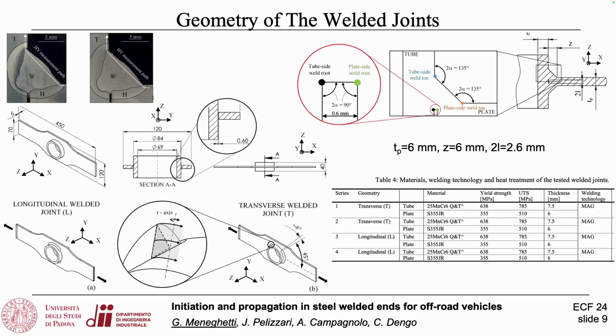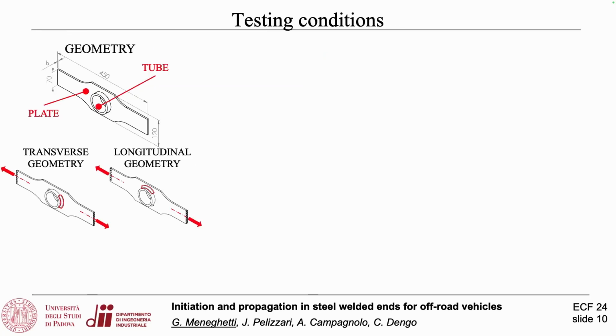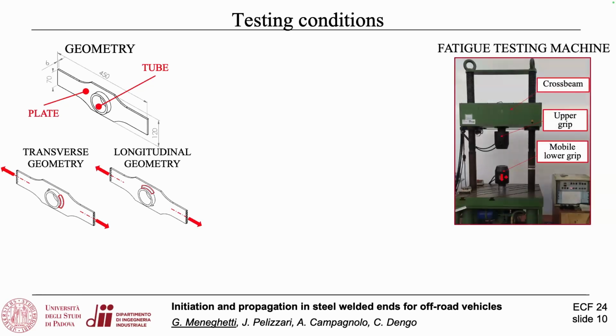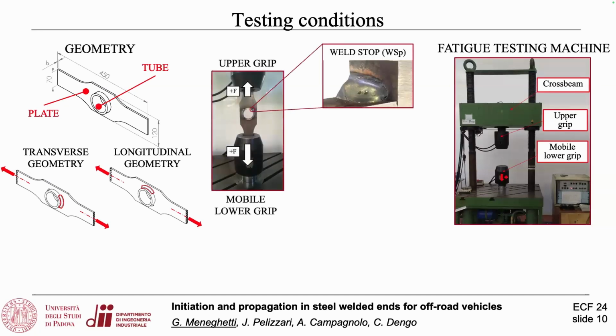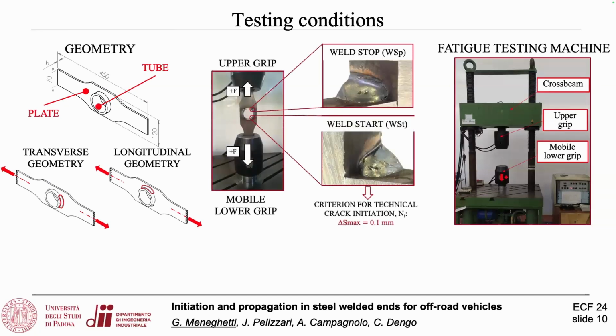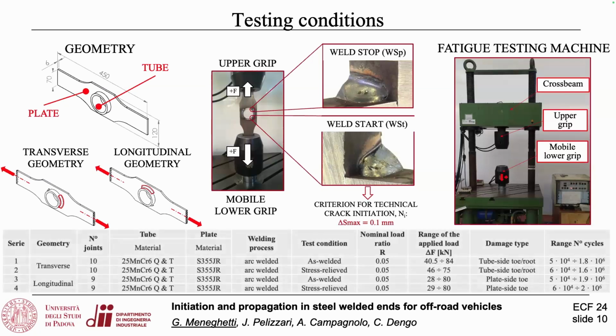We designed 2 versions of the specimens, one with intermittent welds which are almost parallel to the loading direction, and the other one where the intermittent welds are transverse to the loading direction. And this determined the name given to the geometries, longitudinal and transverse joints. So this is the joint geometry. The testing condition was pure axial loading under pulsating tension. And you see here the weld start and stop points with the real geometry.